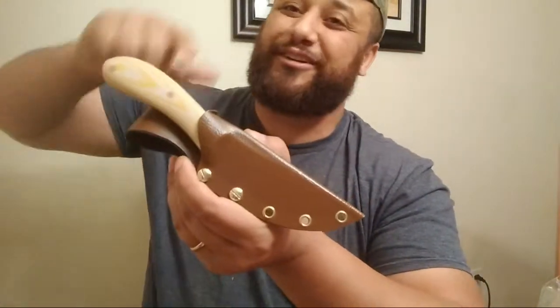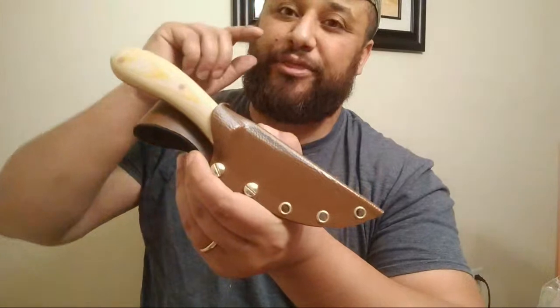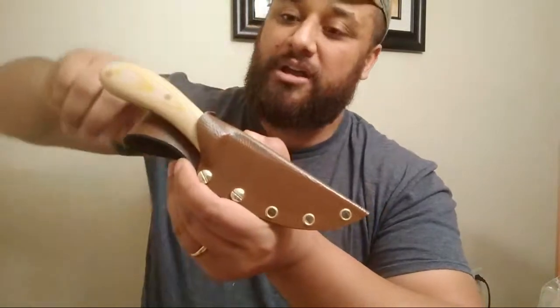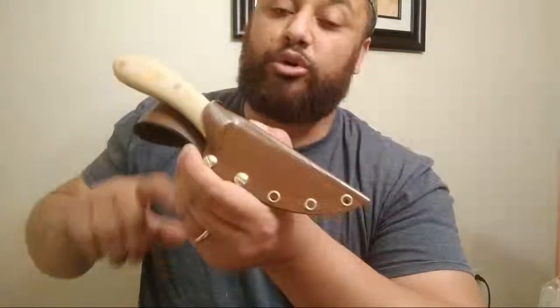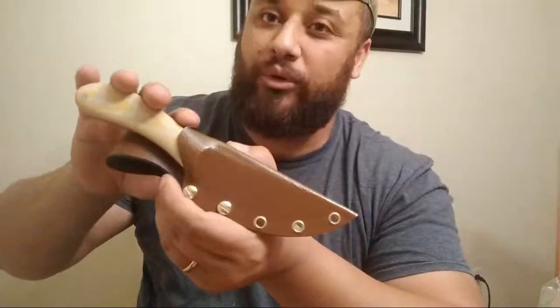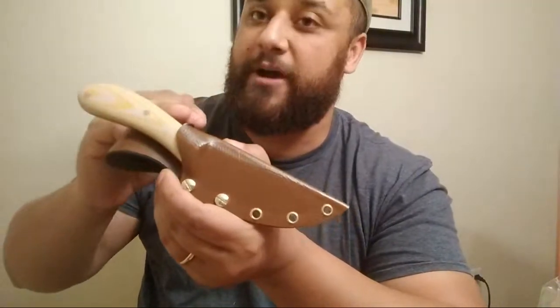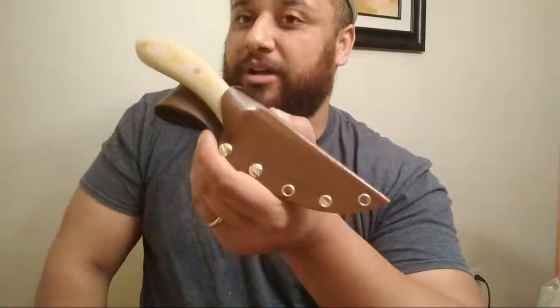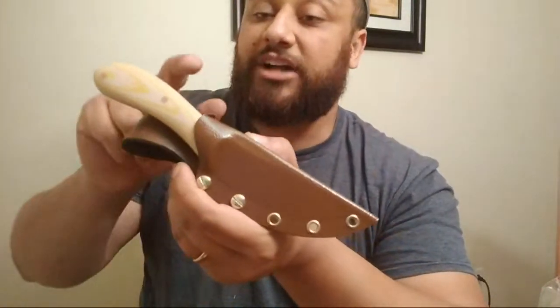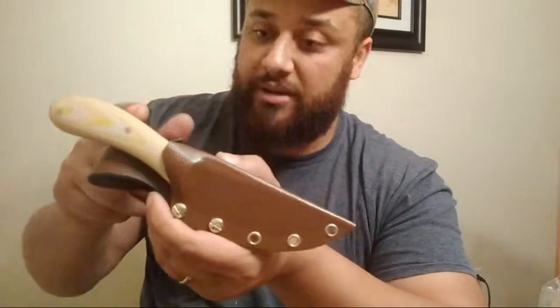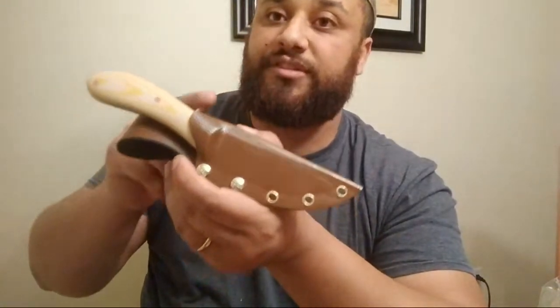Will it cut longer than Rex 121? Fuck no. Rex 121 is a goddamn beast. We have 32% carbide volume. Rex 121 has larger carbides, which technically might actually help it resist being worn down. But we have 32% carbide volume. It's a balance between M6C and MC type carbide. 24% of that is going to be the actual MC type, which is vanadium carbide, and the rest of it is going to be the softer M6C type carbide.